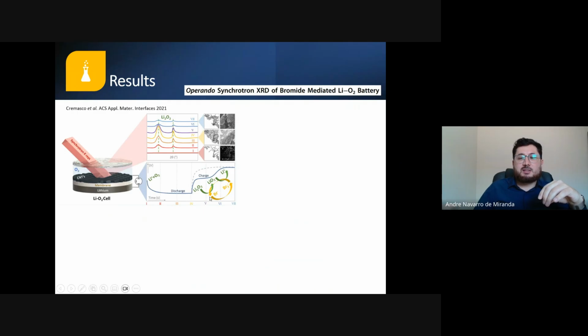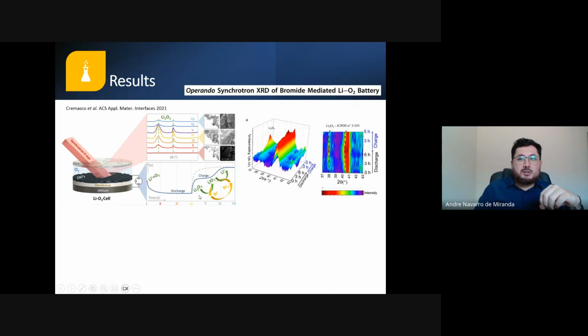So in the process, bromide is oxidized, and it helps in the charge process of the battery. So here is one chart that shows the diffraction pattern. Here's intensity, the degrees, and here's the discharge and charge process. And then we can see the formation of lithium peroxide, and then the decomposition of lithium peroxide. So in this experiment, we could observe the formation and the decomposition, and then we validate our system that is forming this lithium peroxide. It was a really nice step in our group to see that our system was working well.